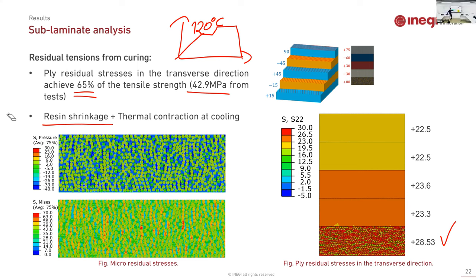Now, you're comparing these strength values, 28, with the value of the strength measured also at room temperature. For example, doing this comparison at 50 degrees, maybe the strength of the composite is another value, but I don't know how much it could be. But I can presume that it will be different, because in the aeronautic industry, they also characterize the composite at 85 degrees, and the materials are considerably different. Not much, but they are different. Okay, that was the question. Thank you. Good.